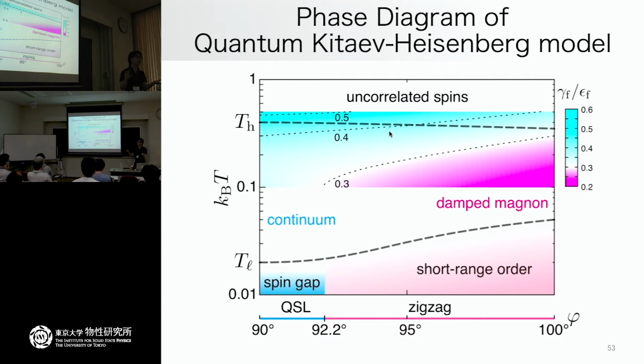But if you do the exact method, like ED, calculating the spectral function, then the gap size becomes much smaller, and we cannot compare with the experimental data. So there is some additional factor in the real compound, ruthenium chloride. And together with this, quite different from the sodium iridate.